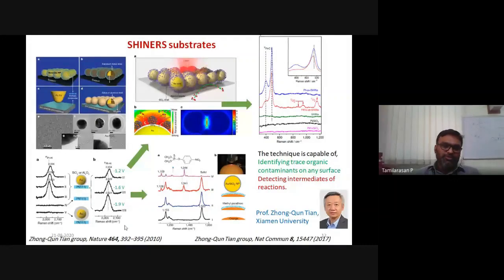some species formation. For example, here, if you take this fourth curve, this is the Pt(111) substrate, where there is a Pt-H formation, hydrogenation. I mean, because of the hydrogenation, there should be a Pt-H formation, and there should be a Pt-H vibration mode in the Raman spectrum, but it was not observed in normal Raman spectroscopy. And even if you put a SHINERS particle with a very thick layer, like 20 nanometer, you are seeing in this image, you are seeing a 20 nanometer thick layer. If you put this layer on this substrate, you are not seeing anything, because the interparticle distance is too much. So the electric field enhancement is completely diminished between this 40 nanometer gap between the two particles, because each particle will have a 20 nanometer shell.